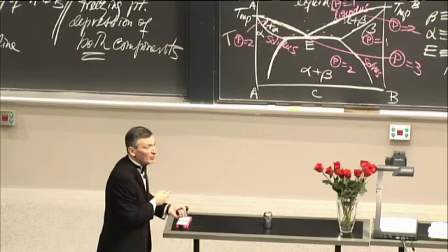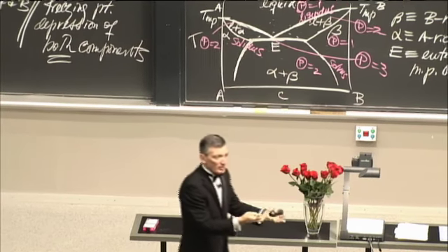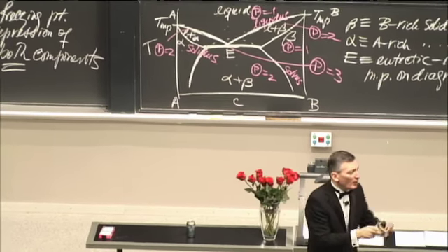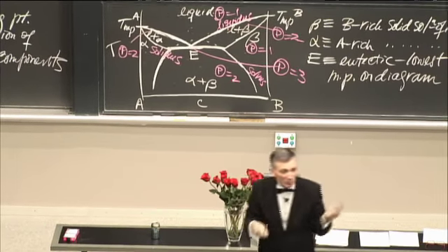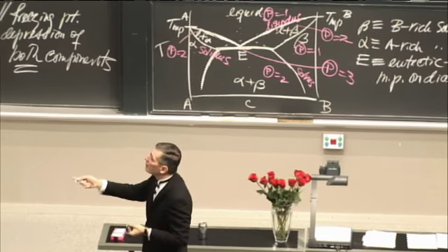And you can see in this regime here. And notice that cubic zirconia, here's a eutectic. Why I'm showing you this is that the zirconia calcia system ultimately becomes eutectic. And the eutectic is at about 2300 degrees C. But over here is the solid solution. Notice, if it's a solid solution, that means it's P equals 1, single phase. As it must be. If it were 2-phase, the gemstone would be frosty, right? You'd have all those internal surfaces and they'd be reflecting. So this is clear and colorless.